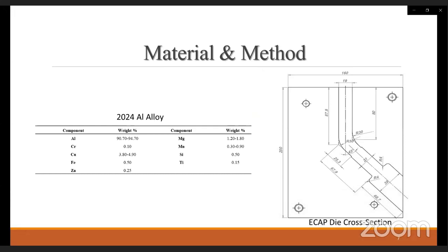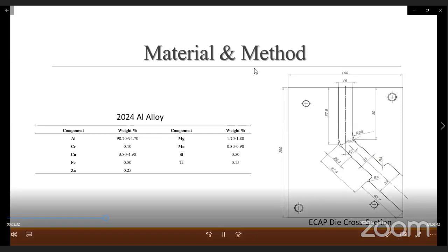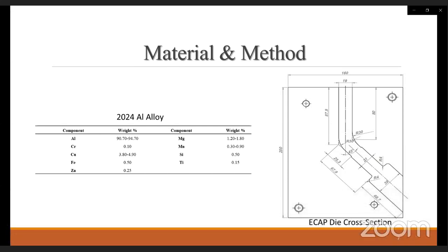The composition is shown on the table, and the aim of this study is to investigate the hardness and microstructural properties of 2024 aluminum post ECAP aging at 175 degrees for 8 hours. And the ECAP process is carried out at room temperature with 1 pass, 2 passes, 3 passes, and 4 passes, with an ECAP die having an angle of 135 degrees. The ECAP die's technical drawing is shown on the screen. These are the exact dimensions.